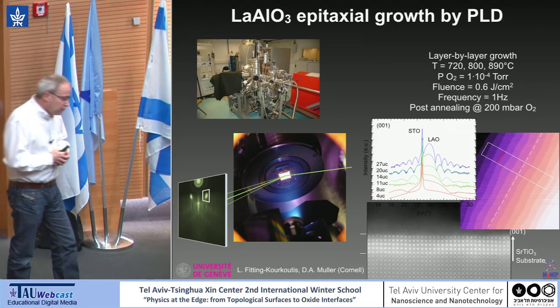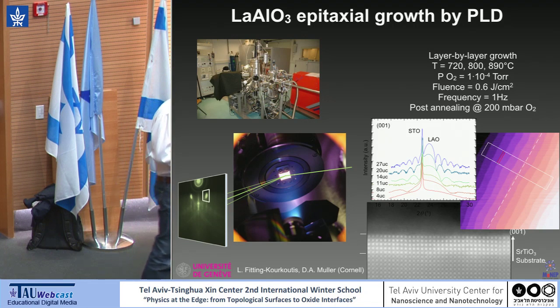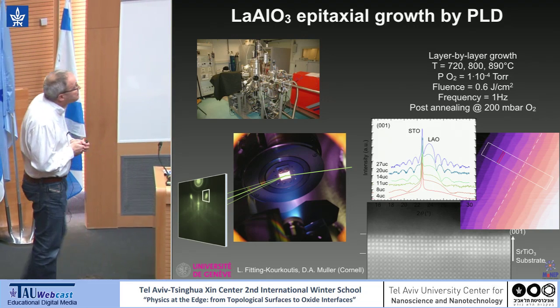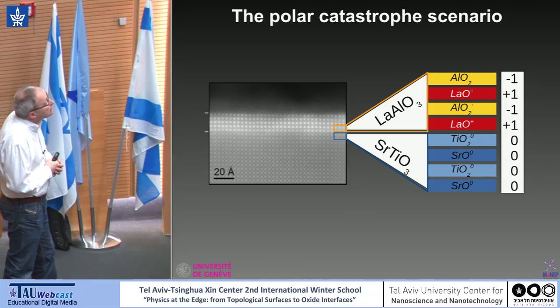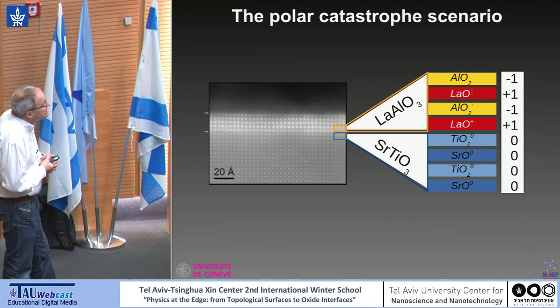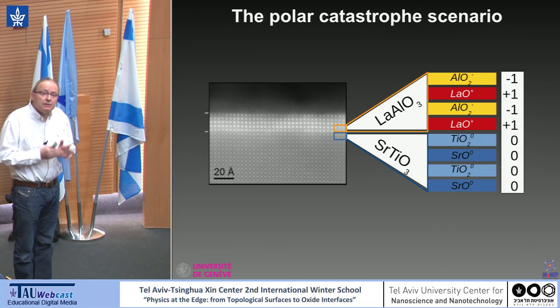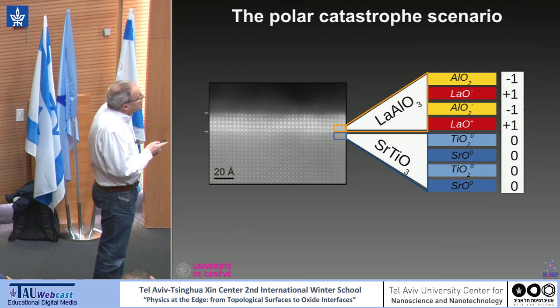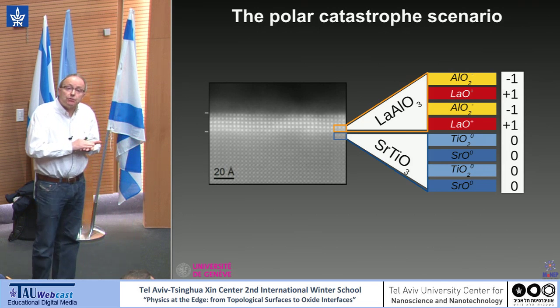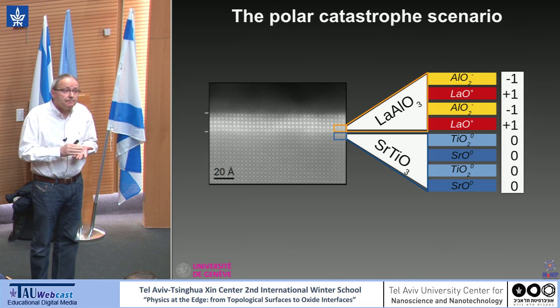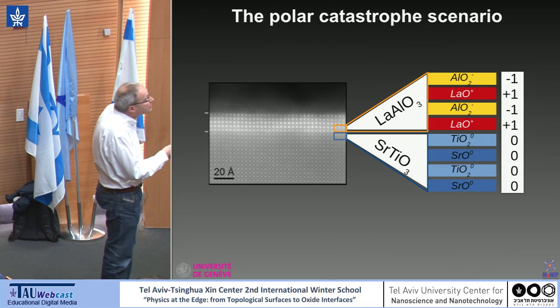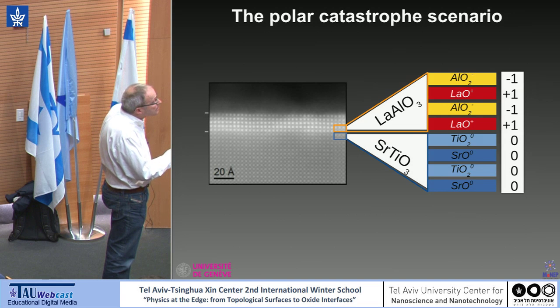Okay, so let me move now to the origin of this conduction. It's been proposed from the beginning by Harold Hwang and co-workers that this conduction may be linked to a polar discontinuity that you find at the interface. This is the so-called polar catastrophe scenario, which in fact is quite simple to understand. If you look at strontium titanate in the 001 direction, you alternate planes of strontium oxide and titanium dioxide. These planes are neutral planes. Strontium is 2+, oxygen is 2-, so this is a neutral plane.